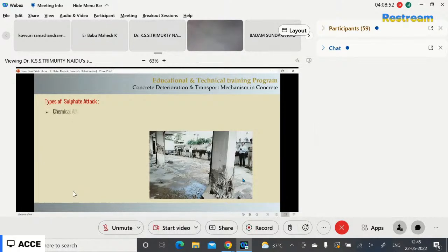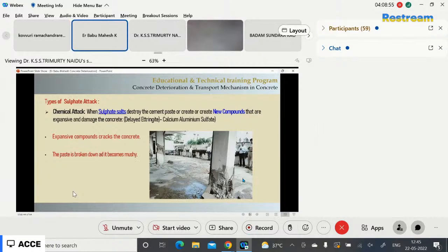Physical sulfate attack means when salts precipitate at the surface of the concrete. In chemical attack, when sulfate salts react with the cement paste, they create new compounds that are expansive and damage the concrete. That new compound is calcium aluminum sulfate, also called ettringite. This is the most expansive compound. It creates cracks in the concrete.